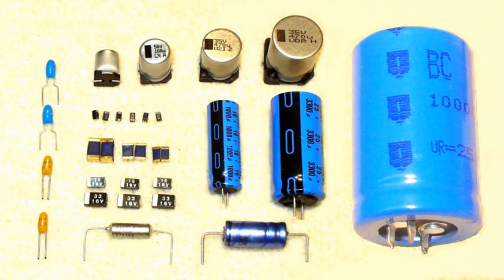The reciprocal value of FIT is MTBF, mean time between failures. The standard operating conditions for the failure rate FIT are 40 degrees Celsius and 0.5 UR. For other conditions of applied voltage, current load, temperature, capacitance value, circuit resistance for tantalum capacitors, mechanical influences and humidity, the FIT figure can be recalculated with acceleration factors standardized for industrial or military contexts. The higher the temperature and applied voltage, the higher the failure rate, for example.